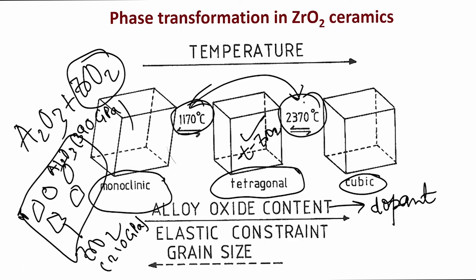So I repeat, there are three effects which influence the zirconia phase stability. The first one is the dopant content, the second one is the elastic constraint, and the third one is the grain size. Grain size means if the grain size increases, then what happens? The tetragonal phase can transform to the monoclinic phase. But if the grain size decreases, then what will happen? Even the tetragonal phase can be retained down to room temperature.